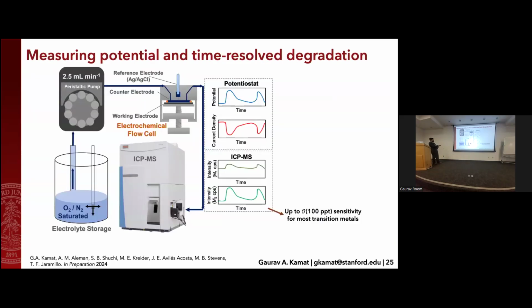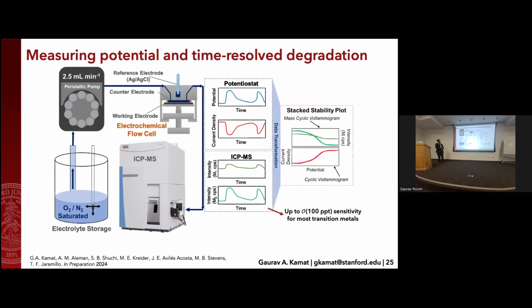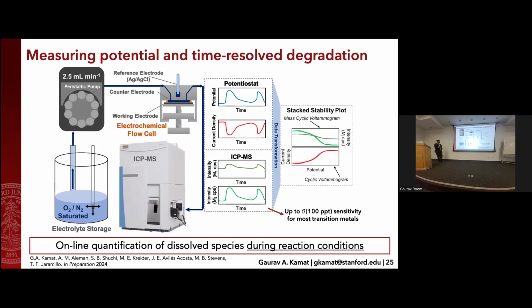And essentially how this works is you take your electrolyte, but instead of putting it in a single reactor, you just pump it through an electrochemical flow cell that has conditions tuned so that it can actually produce realistic current densities. And all the liquid that comes out of there can feed straight into an ICP-MS. It's not that simple. There's a lot of things here at the interface that need to be figured out. But in essence, you have your potentiostat, which is changing your potential and recording the current density, just like all the measurements we've seen. But now your ICP-MS can actually measure any number of dissolving elements as a function of that same time. And if you combine those two data sets, you can have a cyclic voltammogram, but you can also have a mass cyclic voltammogram that says, as a function of potential, where exactly is my dissolution happening? So this is really important because it's online quantification of dissolved species during reaction conditions, during relevant conditions.